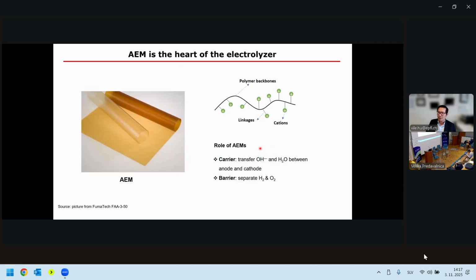Now let me introduce a little bit about this membrane, AEM. It's actually a really thin plastic, and typically is based on a polymer backbone with a linker to a cationic functional group. Okay, these cations then can interact with anions, so that's how it can transport the anion. The role of AEM will have two in this case. One is, of course, to transfer hydroxide, but also we need to transfer water between anode and cathode. The second thing it needs to do is to separate hydrogen and oxygen as a membrane.